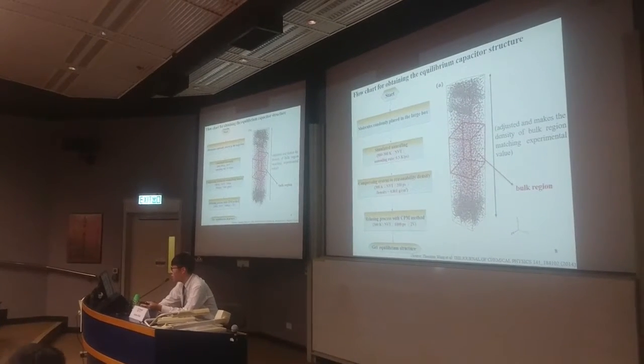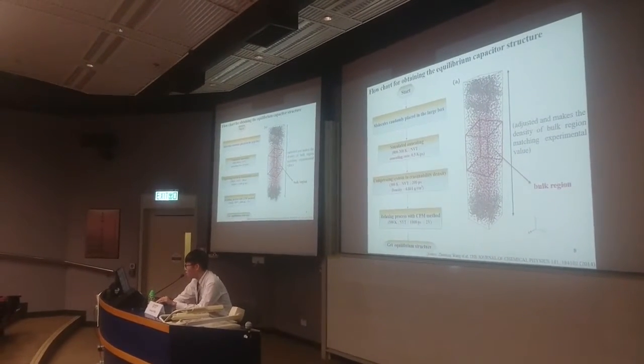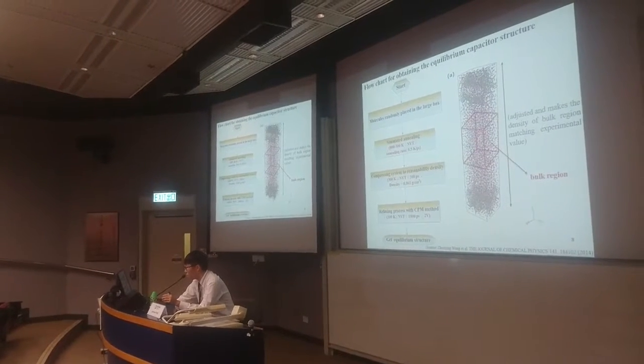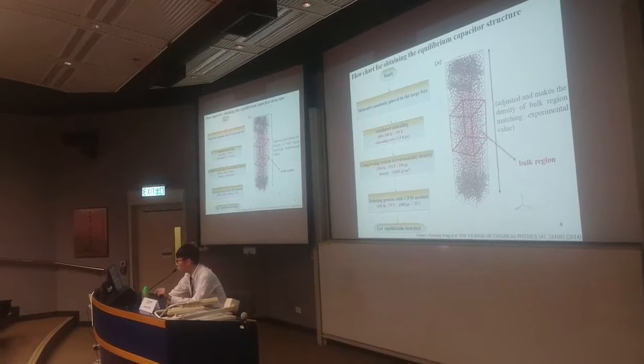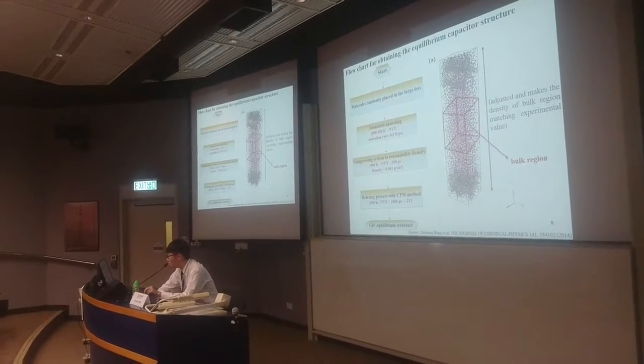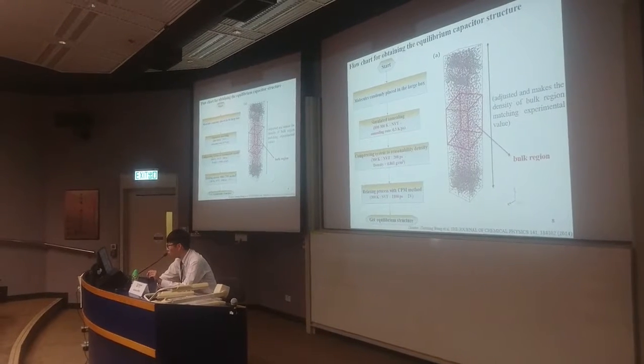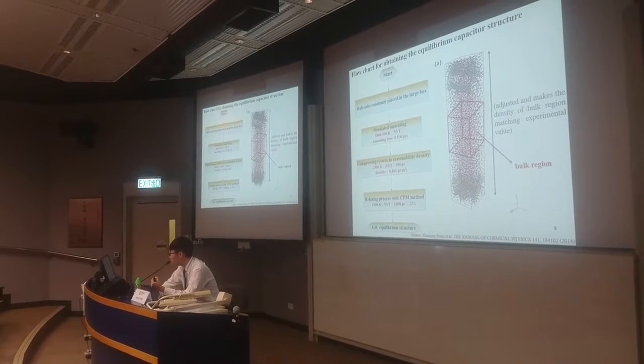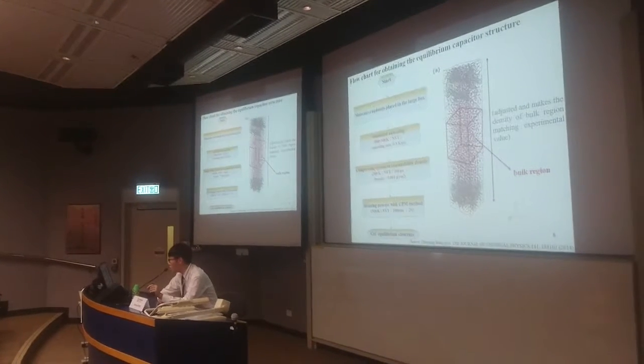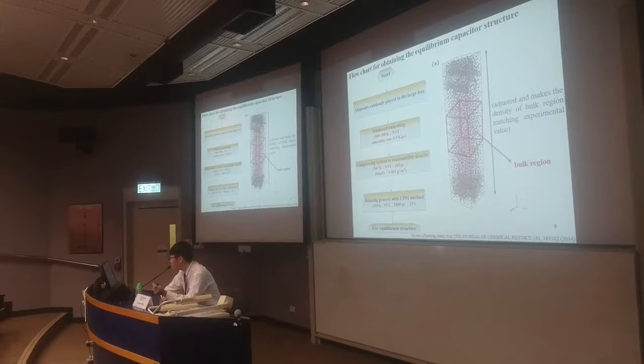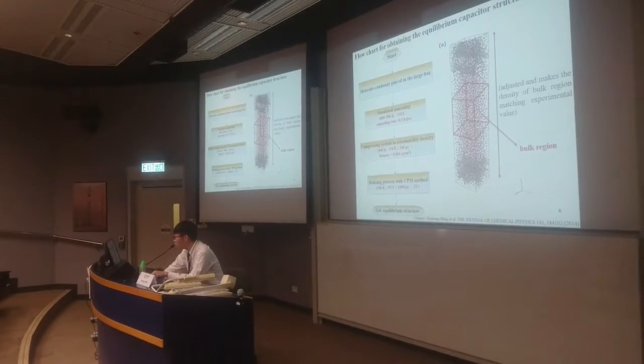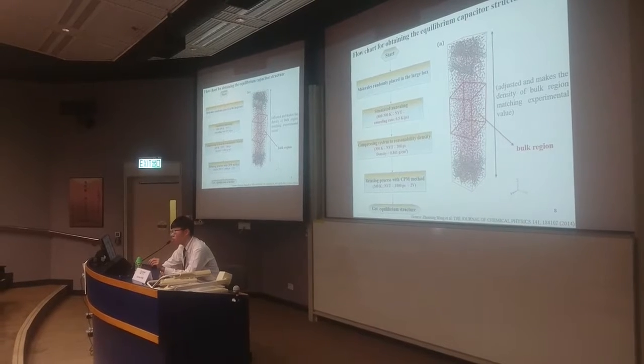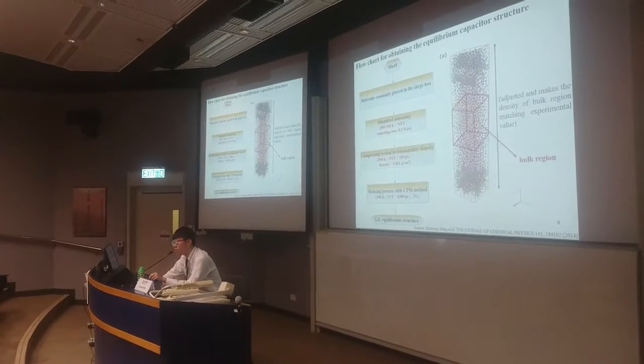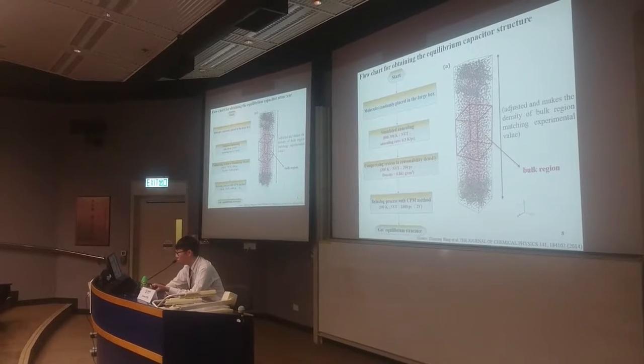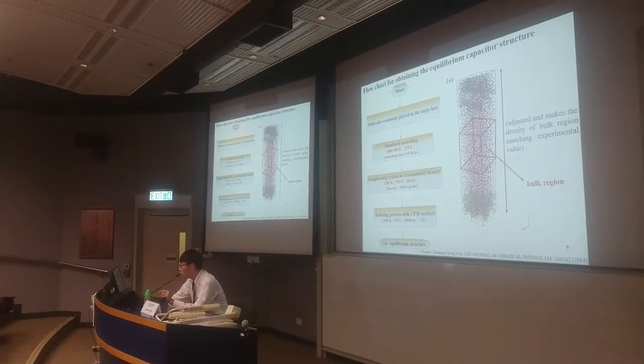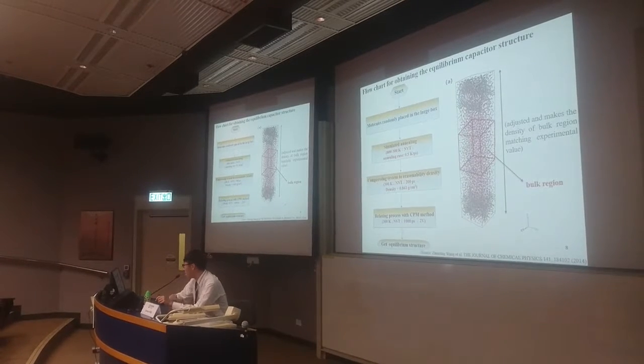First, we place the electrolyte molecules between the symmetric AC electrodes. Then second, the system was annealed from 800K to 300K by MD simulation in the NVT ensemble during 5 nanoseconds. Then third, the length of the box in this direction is adjusted and makes the density of the bulk region match the experimental value. And finally, the electrodes have been charged by the constant potential method under a voltage electric potential for at least 5 nanoseconds until the system reaches equilibrium.